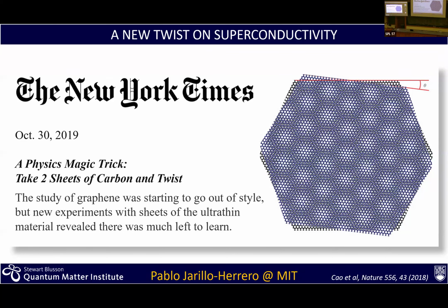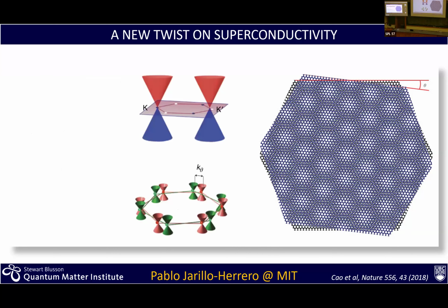Basically, you start off with a symmetry unit, which is very small, capturing basically a hexagon of this graphene layer. But as you make those, you can see that now the modulation is on a much bigger spatial scale. This is work that comes out of the MIT group of Pablo Jarillo-Herrero, and really has raised immense attention in the last few years. And the reason is that as you start twisting and moving these things, you can really engineer the electronic structure of these materials.